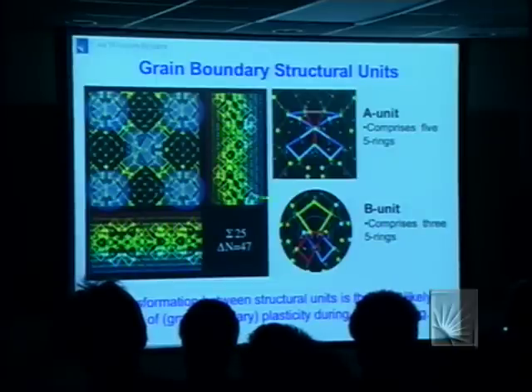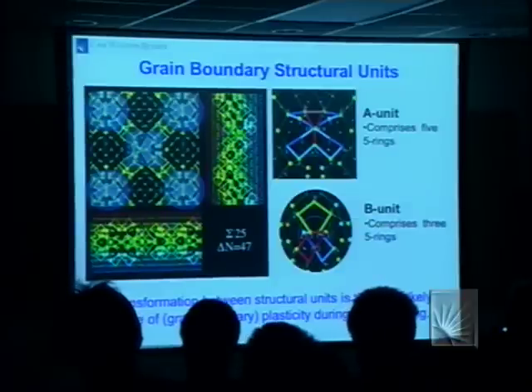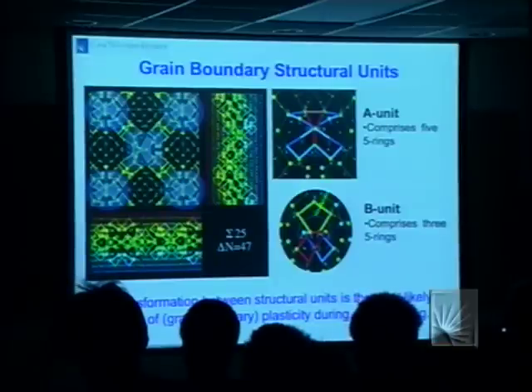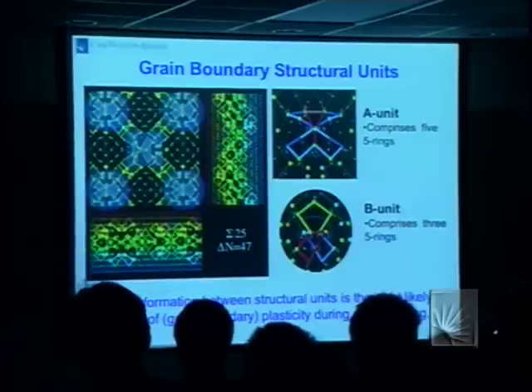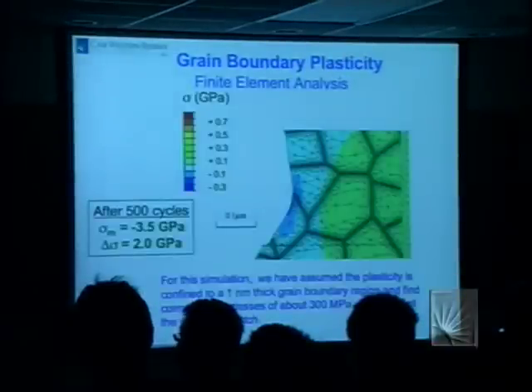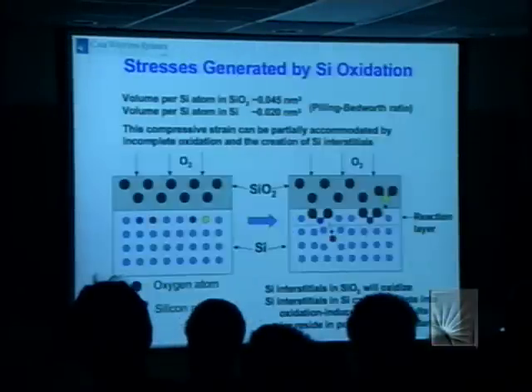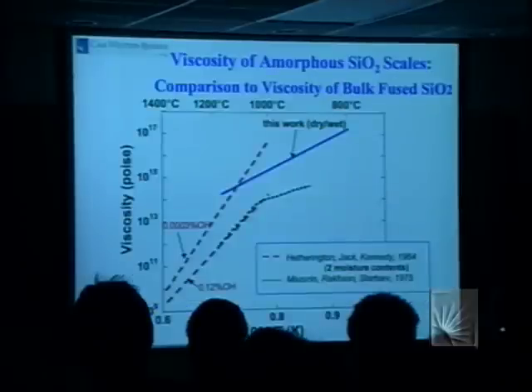And if that happens, that is effectively a form of grain boundary plasticity. Any plastic deformation causes a small change in shape, and if you change A units to B units, that's what you get. We suggest that this must be the origin of what we've observed. I see my time is up. I was too ambitious.